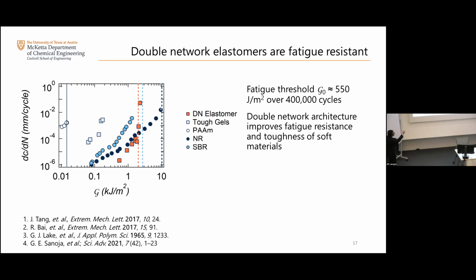In general, elastomers are synthetic in nature, historically natural rubber, styrene butadiene rubber. They have fatigue thresholds on the order of 100, 150 joules per meter square. Gels even lower. Our system actually has a fatigue threshold of about 550 joules per meter square under 400,000 cycles of cyclic load, meaning that you actually have a pretty fatigue resistant material. So the first observation that we have is that these architectures are actually pretty fatigue resistant, and they're still tough. They have toughness that is comparable to that of styrene butadiene rubber.